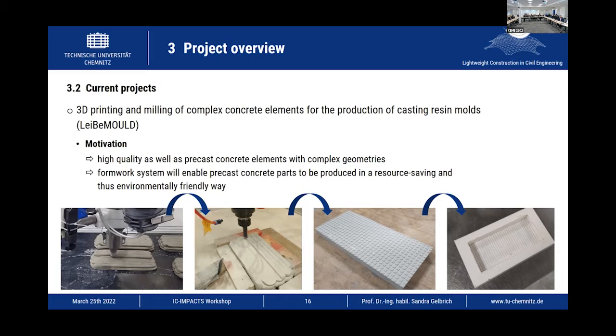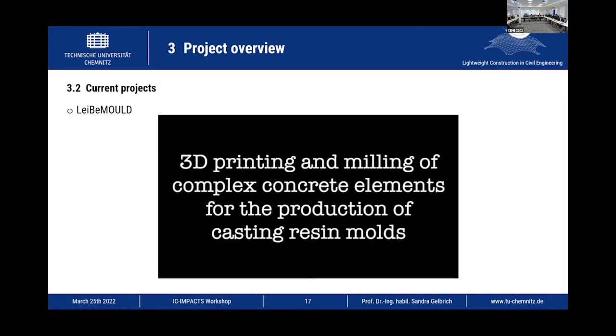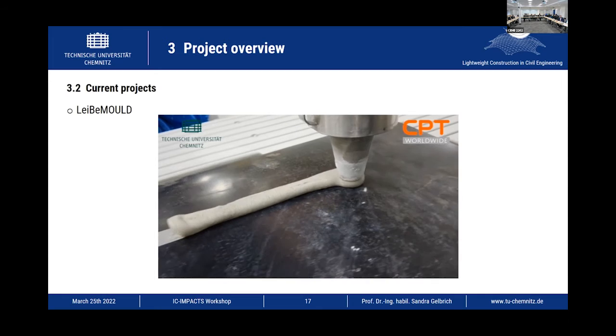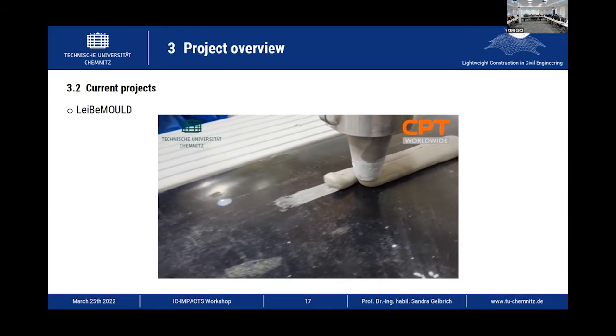Therefore, a material with a very small maximum grain size was developed, and the developed concrete can be printed close to the final contour and then milled to the exact contour when cured. And in the final step, the model can be molded with a suitable casting resin. Here you can see a short video sequence which shows the steps as mentioned.